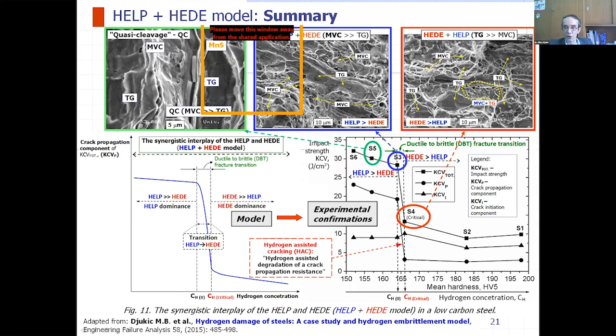In the case of S4, when we have a sharp drop of mechanical properties, crack propagation resistance, and also total impact strength, we have a very similar situation, but as you can see, we have a predominance of transgranular quasi-cleavage fractured area due to dominance of the HEDE mechanism, with the remaining area still fractured ductilely by microvoid coalescence due to activity of the HELP mechanism. So in this case, we have a dominance of HELP, and in this case, a dominance of HEDE. And as you can see, we have a model and experimental confirmation of the sharp drop and ductile to brittle fracture transition in steel due to activation and predominance of the HEDE mechanism.